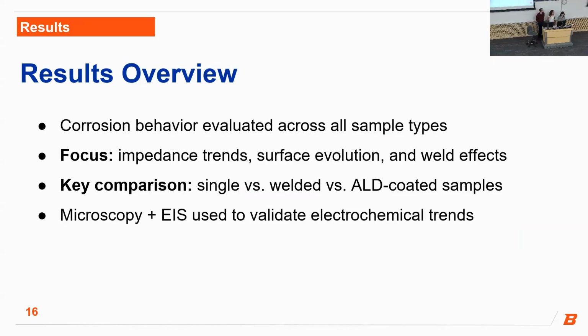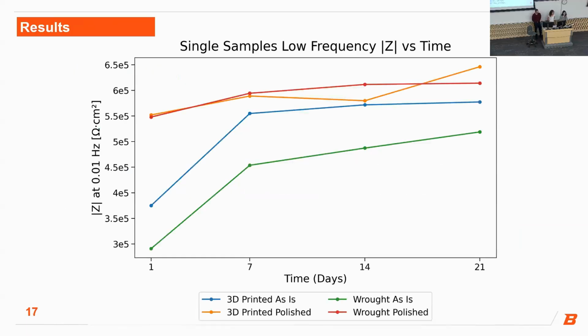So beginning with our baseline single samples, we took the impedance magnitude values at a frequency of 0.01 hertz and plotted it versus time to evaluate how the surface evolves during exposure. These impedance values were taken from the Bode plots of all of our samples after their 4 EIS measurements. We use 0.01 hertz because at a low frequency, the AC signal reflects the overall resistance to charge transfer across the surface of each sample.